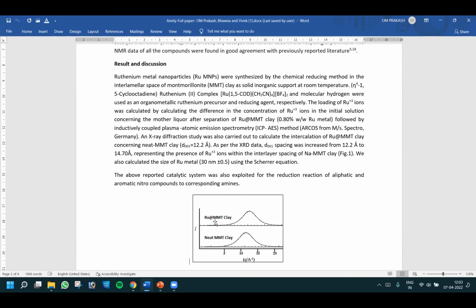The loading of ruthenium ions was calculated from the difference in the concentration of ruthenium ions in the initial solution and in the mother liquor after separation of the ruthenium MMT clay, followed by inductively coupled plasma atomic emission spectrometry. An X-ray diffraction study was also carried out to confirm intercalation of ruthenium in the MMT clay.